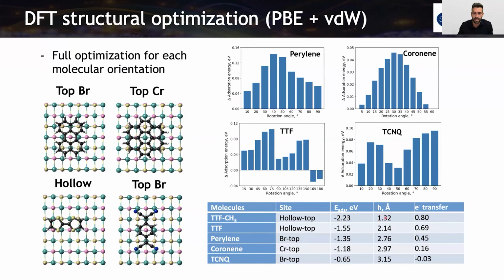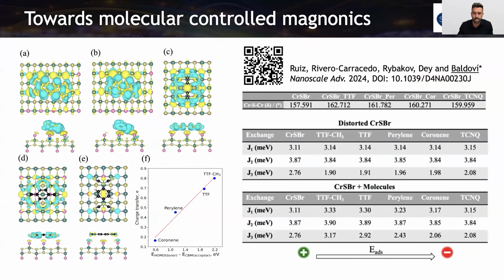And this is the distance between the molecule and the surface. In this case, it gets closer and it provides more charge transfer. So we are increasing the donor character of this molecule. We can control the charge transfer that is donated to the substrate. Here are the charge density representations. In this case, this blue cloud here means a depletion. So it's a donor, it's donating electronic density, and the bromide is accepting.